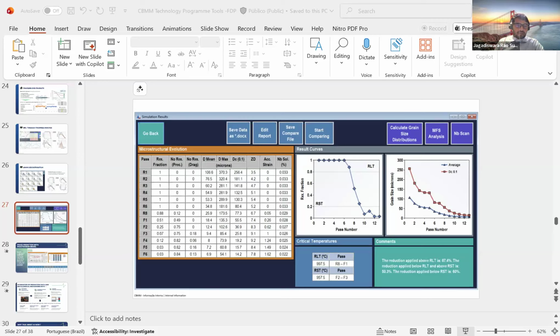And the phase prediction model, okay, this is an additional model recently developed, particularly for once the rolling is completed, based on the cooling rate. It is a simple continuous cooling transformation model, but with a real chemical composition, and it takes the input of the prior austenitic grain size after the last rolling stand, either a finishing mill or another type of mill. Based on that, it gives the fractions of ferrite, pearlite, bainite, and martensite, and it is also validated with some real steel manufacturers.